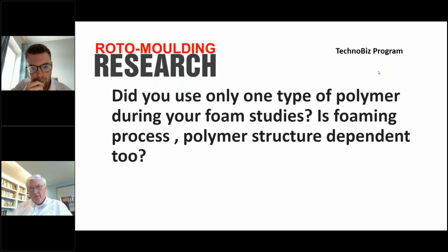So to answer the first question, the only polymer that I have described in my thesis is polyethylene. I also looked at using nylon and polypropylene as well. The problem with that, though, was that I'm temperature limited in my experiment to 200 degrees Celsius on the heating oil side. So I couldn't get comparable results. The foaming process, though, is definitely polymer structure dependent as well.